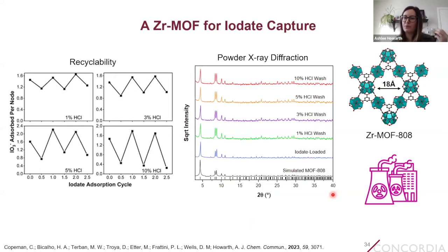We can also reuse and recycle this MOF adsorbent. So when we take the MOF loaded with iodate and expose it to hydrochloric acid at increasing concentrations, we can see that we can remove some, in the case of low concentrations of acid, or nearly all of the iodate oxyanions when using higher concentrations of acid. So we can adsorb the iodate, remove it, adsorb it, remove it, and do multiple adsorption-desorption cycles. And throughout all these cycles, we can see that the MOF remains robust. The powder X-ray diffraction patterns show that it's still crystalline and phase pure, regardless of the concentration of acid that we use, and up to at least 3 cycles, which is what we've tried so far.